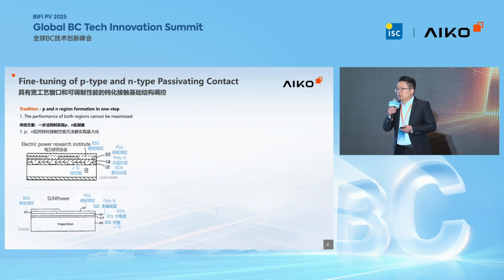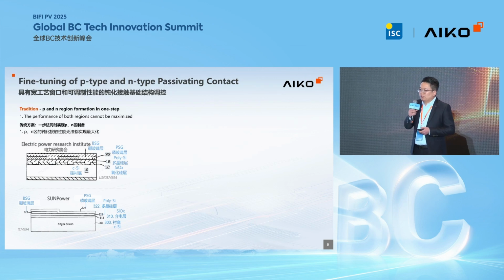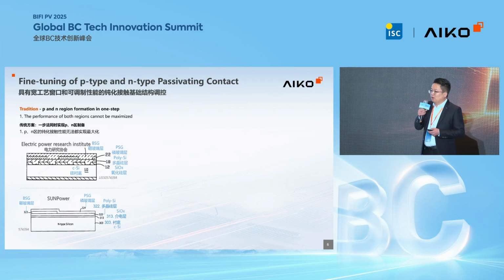So in traditional technology, the P and N regions are formed in the same step by forming the same tunnel layer and diffusing the phosphorus and the boron from the PSG and the BSG. But due to the different diffusion coefficients of the dopants, the one-step method cannot achieve the best performance of P and N passivating contacts at the same time.